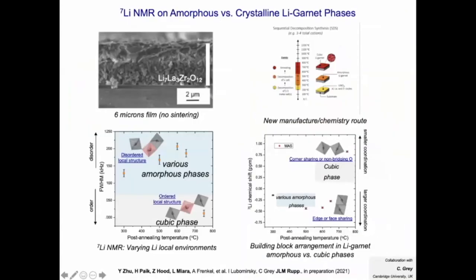Now, when we looked into that and tried to understand the structures, I want to highlight the work of Yuntong Zhu and Hyun Paik and many others in the group, and also a good collaboration with Igor Lubomirsky at the Weizmann, Anatoly Frenkel at Stony Brook and Clare Grey in Cambridge. We were interested in trying to understand how we describe these amorphous phases. As mentioned, you can make these also as amorphous by either SDS or PLD. And when we look, for instance, at lithium NMR, what's really exciting is that depending on the post-annealing temperature, where I show it here with my cursor, we're everywhere still amorphous, but we can find very different lithium hopping dynamics.